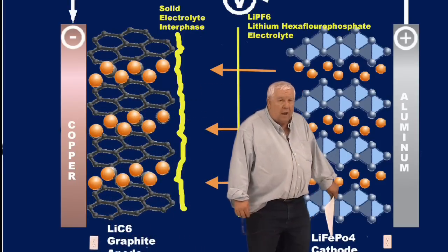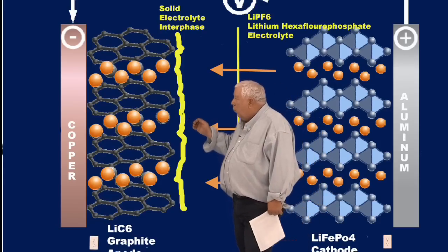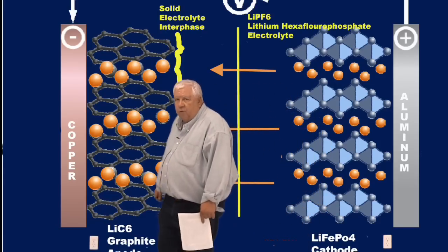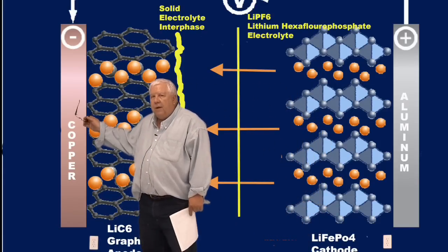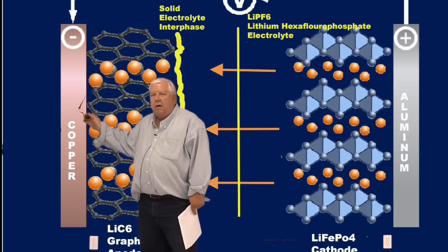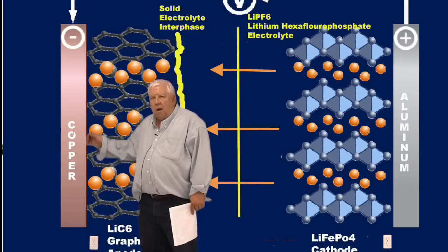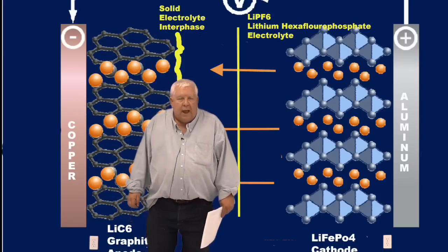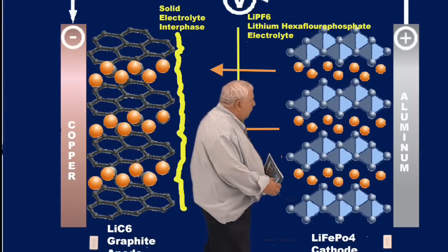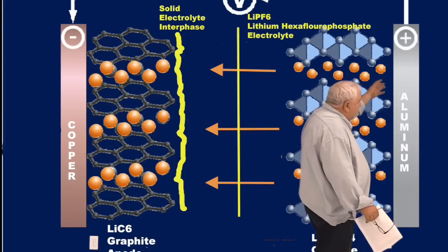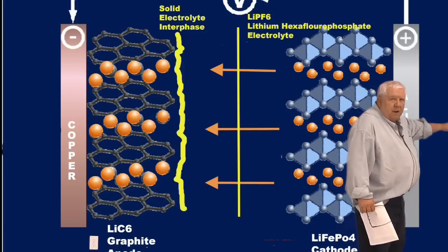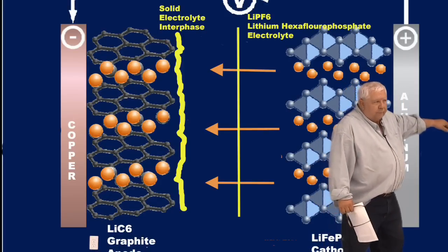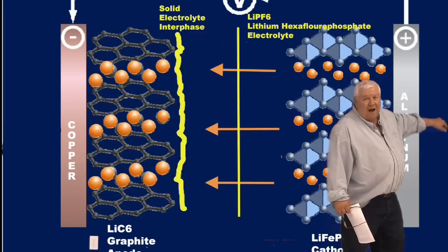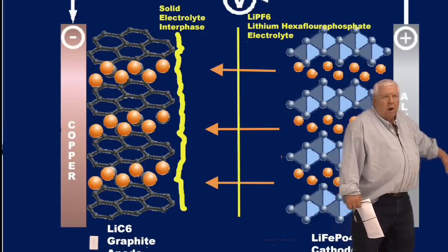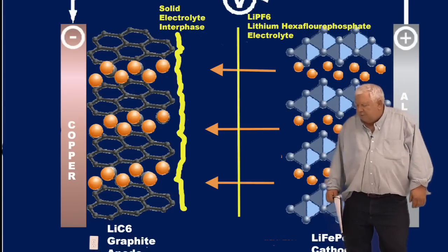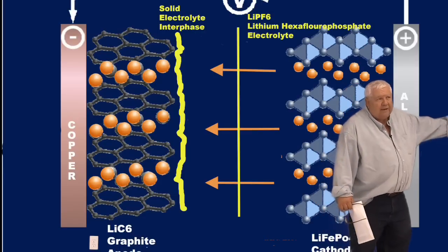But if we do it enough where we short this cell, it will go into thermal runaway and you'll have quite a fire. And it feeds on itself. As it goes into runaway, it gets hotter, the SEI layer melts, and this thing takes off. At some point, it gets so hot that our cathode begins to dissociate oxygen out of this 1 Fe atom, 4 oxygen atoms, and 1 phosphorus atom. The phosphorus actually stabilizes this quite a bit.